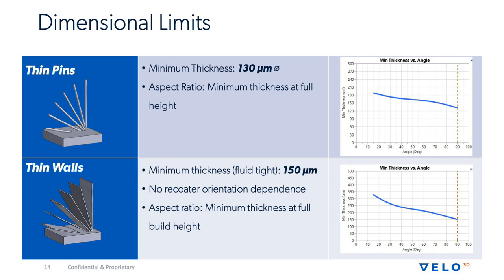So for thin features, the minimum thickness of a pin is about 130 microns. Minimum thickness for a wall that is fluid tight and non-porous is about 150 microns. And both of these behave similarly in that the minimum achievable thickness is a function of angle. Because of the layered nature of the process, at 90 degrees, remember this is vertical, for a pin it's about 130 microns, but as the angle goes down and approaches horizontal, the minimum achievable thickness is a bit larger. It's up more towards 190 or 200 microns. Same thing for the walls, although the dimensions are slightly different.